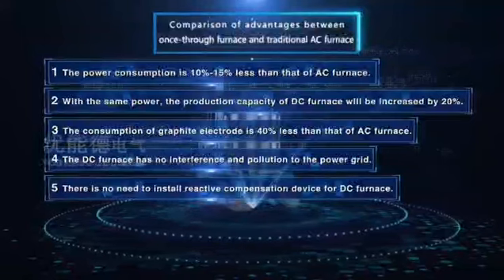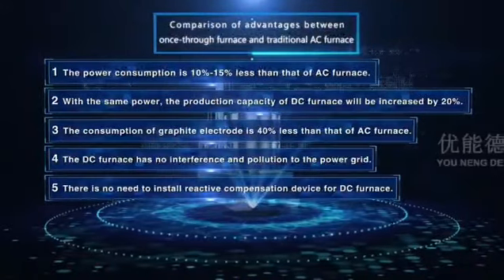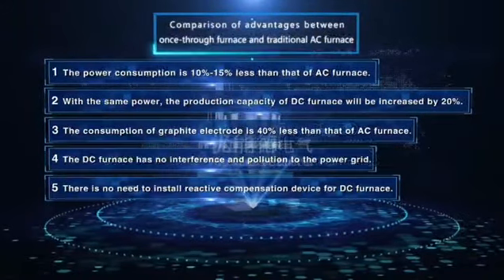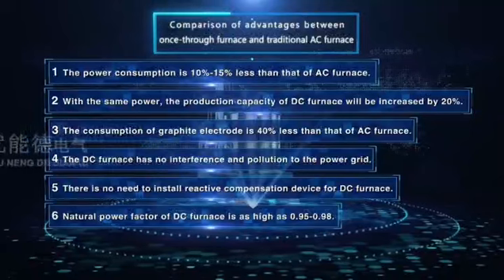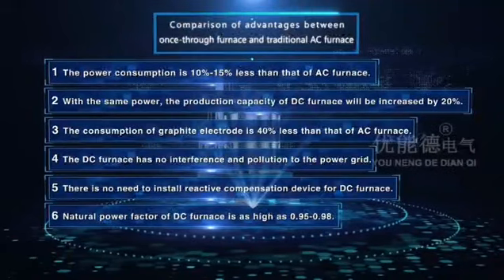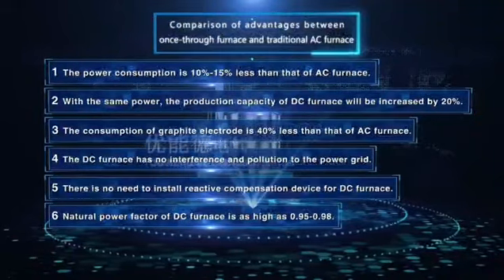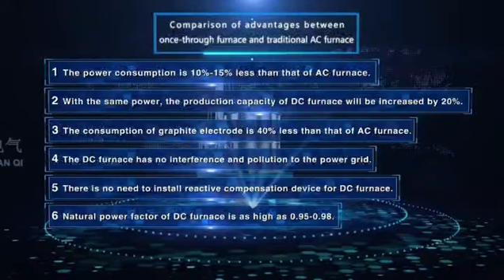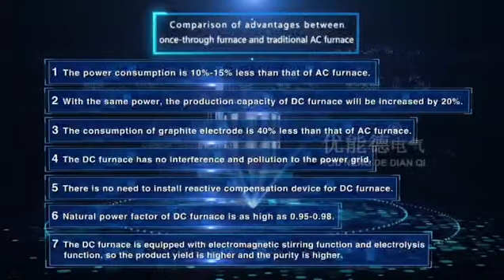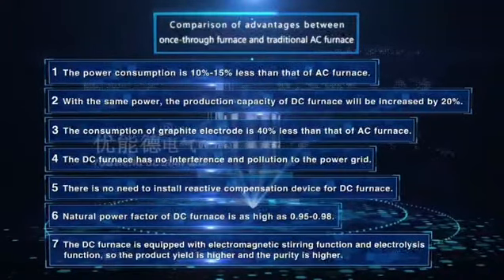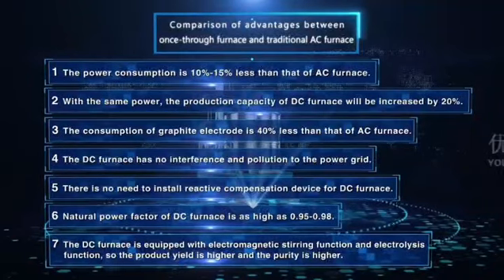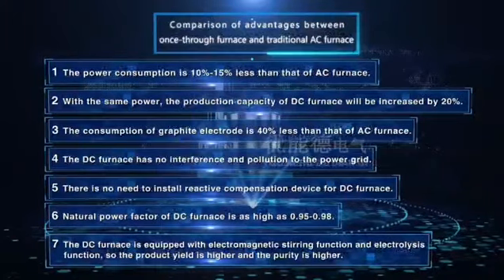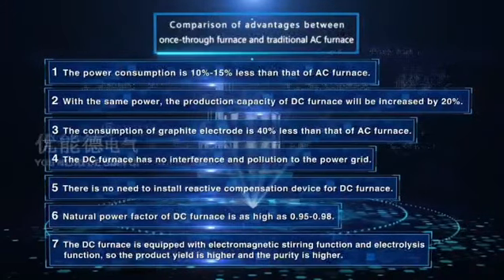5. There is no need to install a reactive compensation device for DC furnace. 6. The natural power factor of DC furnace is as high as 0.95 to 0.98. 7. The DC furnace is equipped with electromagnetic stirring function and electrolysis function, so the product yield is higher and the purity is higher.